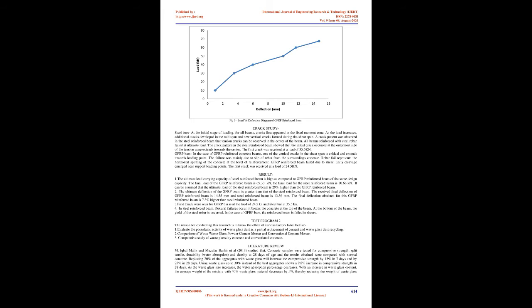Crack study. Steel bars: at the initial stage of loading, for all beams, cracks first appeared in the constant moment zone. As the load increases, additional cracks developed in the mid-span and new vertical cracks formed in the shear span. A crack pattern was observed in the steel reinforced beam that tension cracks can be observed in the center of the beam. All beams reinforced with steel rebar failed at ultimate load. The crack pattern in the steel reinforced beam showed that the initial crack occurred at the outermost side of the tension zone and extends towards the center. The first crack was observed at a load of 35.5 kN.